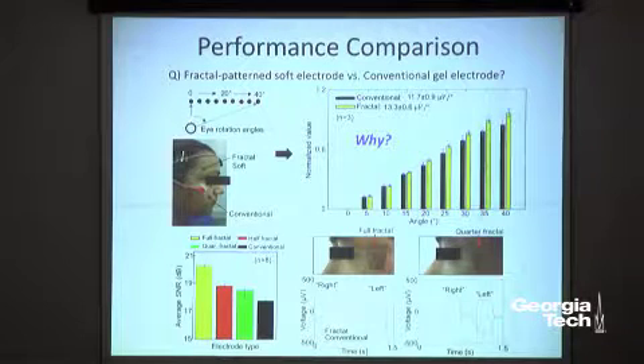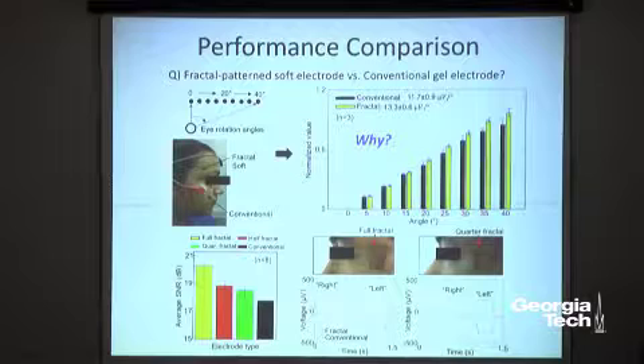But instead of that, our electrode is completely soft and conformably laminated onto the skin. So we don't need to use those overall adhesion areas. So compared to that, we are getting a bigger surface area compared to the gel electrode. So the fractal, quarter size of the electrode is similar to the conventional electrode, which is good. We are getting a higher signal-to-noise ratio with comfortable lamination.